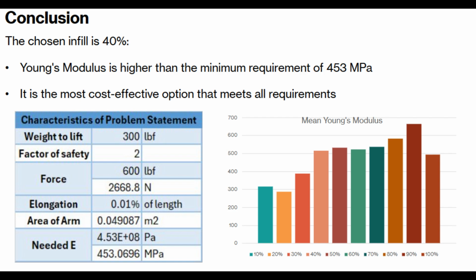On the right, we can see a chart with the mean Young's modulus for each of the infills. The chosen infill is 40%. But why? First, because the Young's modulus is higher than the minimum requirement of 453 megapascals. However, from 40% to 100%, all of them meet this requirement. However, we choose 40% because it is the most cost-effective option, since it uses the least material of all of them.